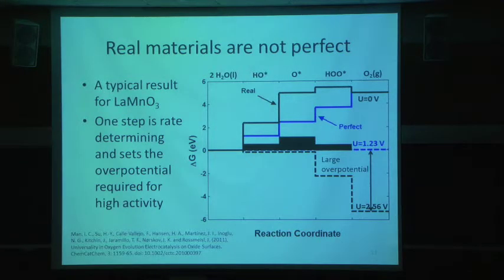That means you have to go from something that is stable to less stable and back down. That's like a reaction barrier that's going to slow down the progress. In fact, if you want all of these steps to be exothermic, you have to apply an additional 1.23 volts so that every step is downhill. This is the origin of the overpotential that's required on a particular metal oxide. You have to apply enough overpotential so that all steps are downhill to make the reaction proceed at a practical rate. So you might hope, well, I showed you lots of materials.